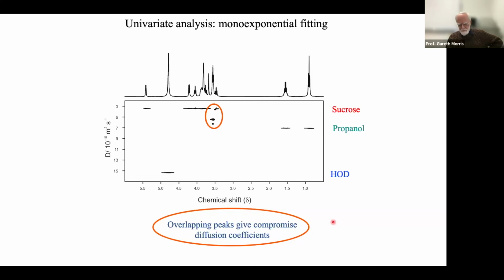So the obvious thing here is to say, well, let's suppose that we have a maximum of two different species contributing to each peak. Then we can just do a bi-exponential fit, get out the two diffusion coefficients, and everything will be fine.